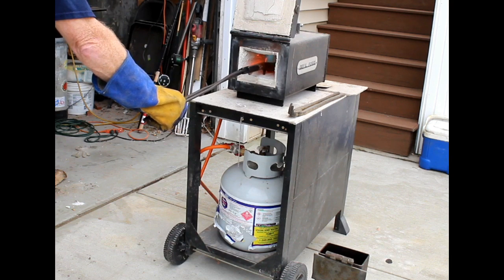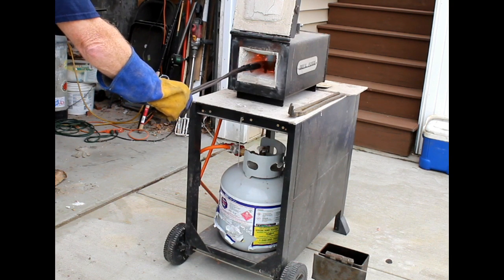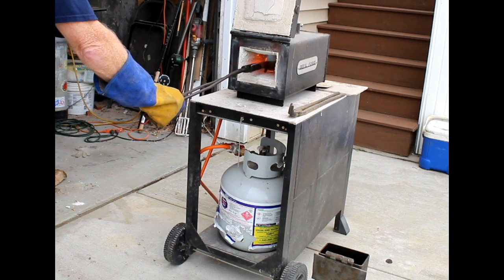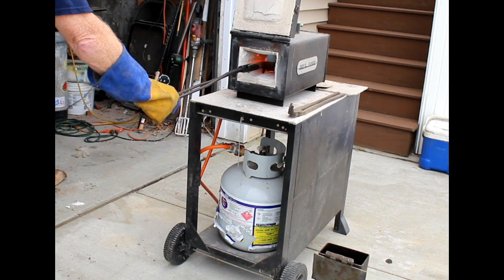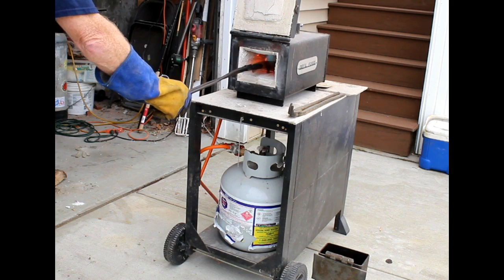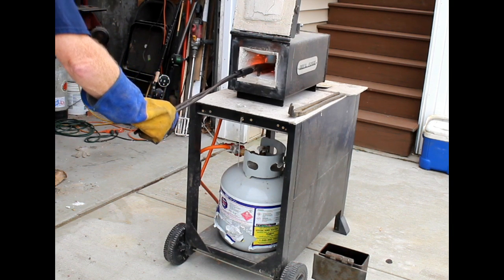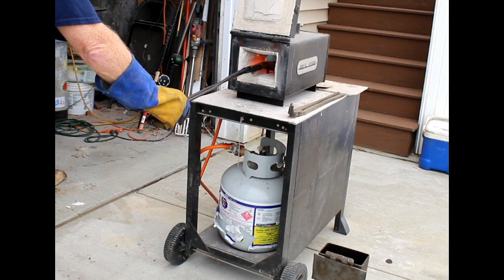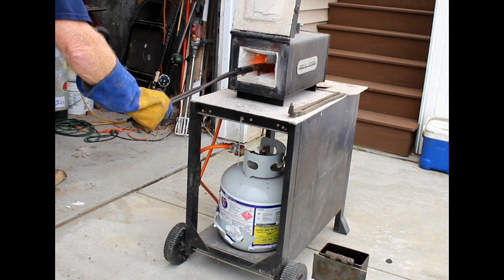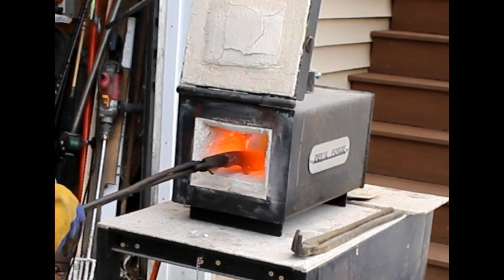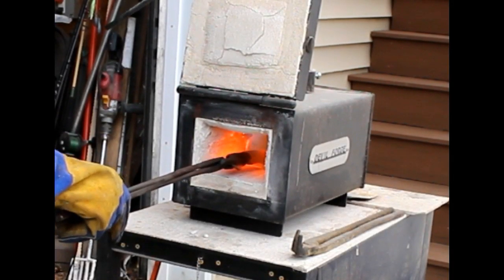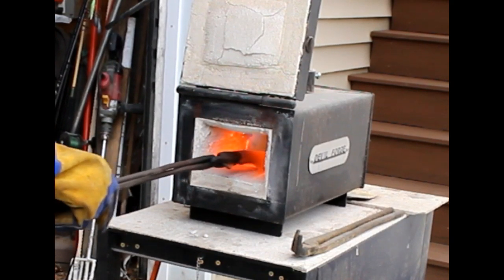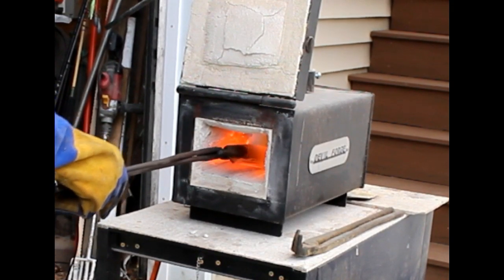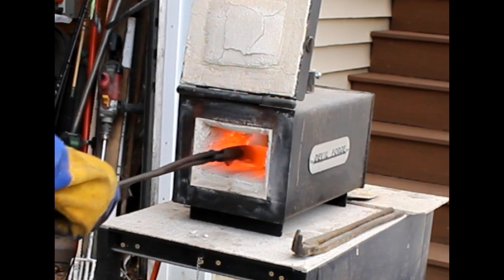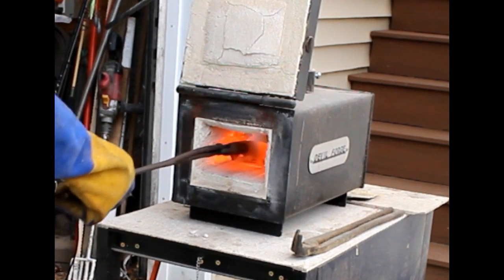Now, the whole trick to heat treating 1095 is to bring it up to non-magnetic. I've got a little magnet attached to the outside of the forge, right up by the top of the door. So I can very easily take the blade out, touch it against that magnet, see when the blade has reached the non-magnetic state, and then I just take a visual note of that color. And you want to hold the blade at that color, without creating any hotter areas, for a couple of minutes. If you can hold it for 2 or 3 minutes, that would be perfect. And then you quench it very quickly into oil.